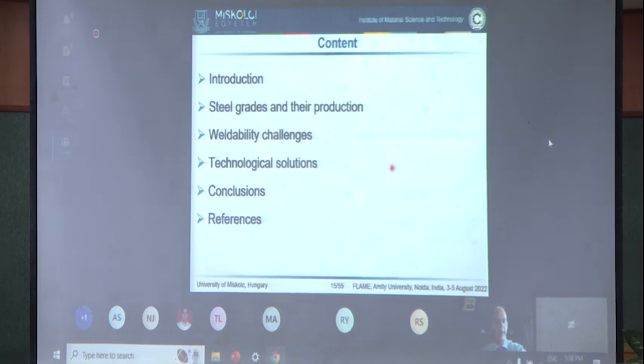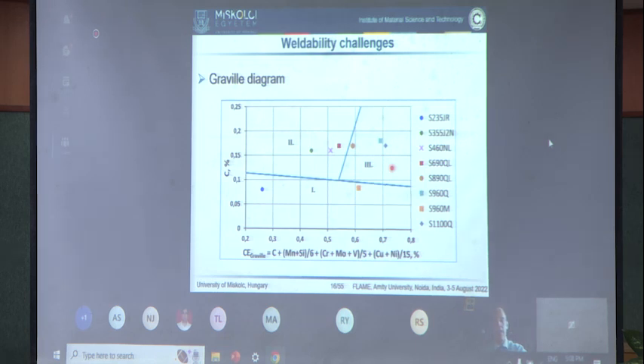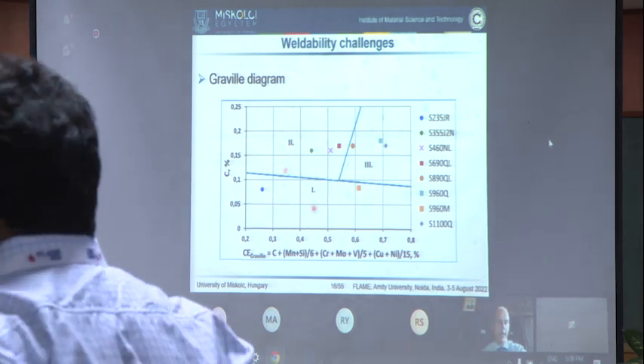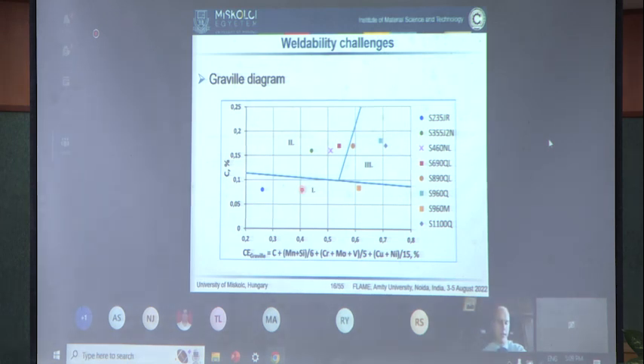Now I would continue my presentation with the weldability challenges. If we consider the weldability of different kinds of structural steels, the best option, if we use the Graville diagram, actually this diagram has three areas. In the first area you can find those steels which are very easy to weld without controlled heat input and preheating. In the second zone you can find steels which are a bit more problematic, but generally they can also be welded without any cold cracking. And in the third area you can find the most sensitive steels, where high cold cracking sensitivity is identified and where you need to use preheating and also controlled heat input.